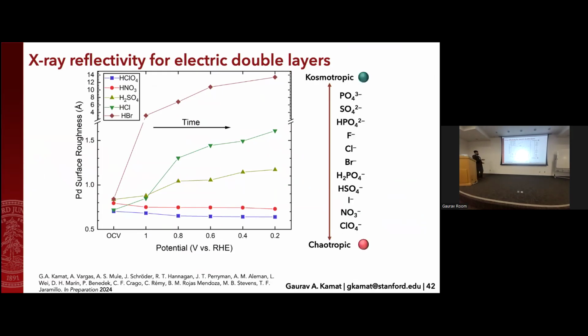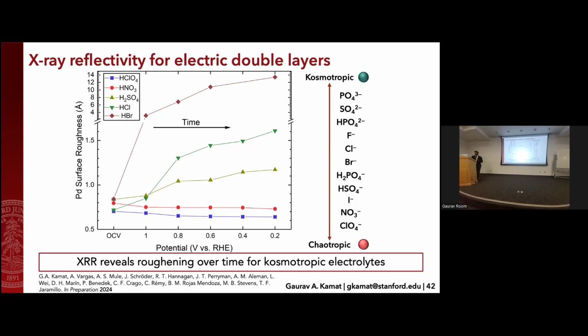And it's interesting because this trends almost exactly with this setup that we had before, where you have chaotropes that do very well in terms of not encouraging surface roughness. And then you have others like bromide or bisulfate that do a lot more. Now, I'll mention roughness isn't necessarily a bad thing. If you roughen your surface, you can open up a little bit more electrochemically active surface area that your material can take advantage of. So if you found conditions in which you can roughen your surface without dissolving it, that may actually be beneficial to the catalysis that you want to do.